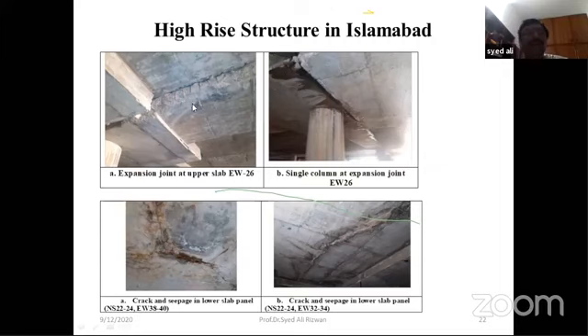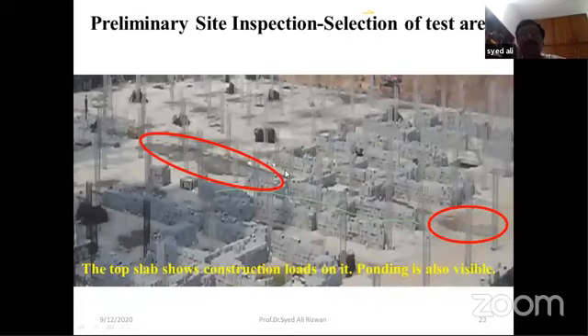And you can see the poor quality of concrete and sometimes the bearing inadequate expansion joint. And then you can see combined cracking and seepage in the lower panel. Crack and seepage you can see over here. Then what they had done after that, they put huge localized loads on the site. And again, this was a case of a runaway contractor.